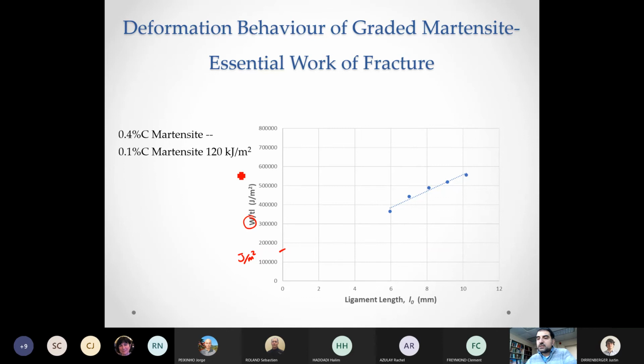So when we tried this test on a steel with 0.4 carbon martensite, all the samples failed randomly at very small stresses because the material is very brittle.